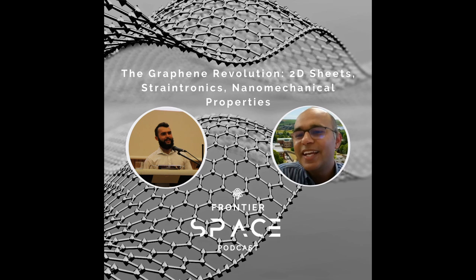One more interesting piece of information that I can tell you, which is hardly explored, but we have recently submitted a paper. These defects also increase the Joule heating effect. It means the thermal performance basically degrades, but it increases the temperature. This work is in collaboration with KAUST. Professor Omer is in charge there. We produced CVD graphene nearly 100 nanometers thick, and it has lots of wrinkles and some edges. When we apply a potential bias of around 7 volts, which is not so high, we get a temperature of up to 300 degrees centigrade, and we heated it continuously for 12 days. Nothing happened to it. So with just 7 volts, you can get 300 degrees centigrade. The continuous performance was nearly 250 degrees centigrade.